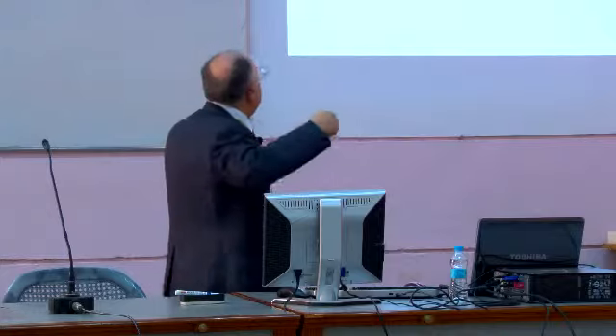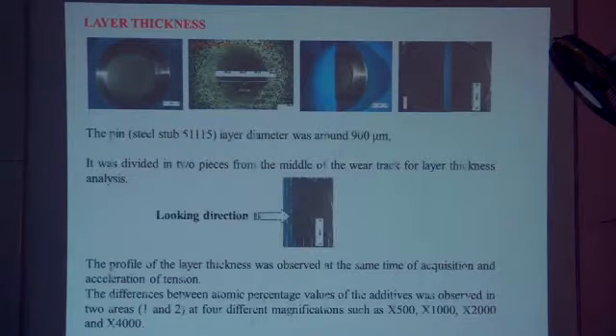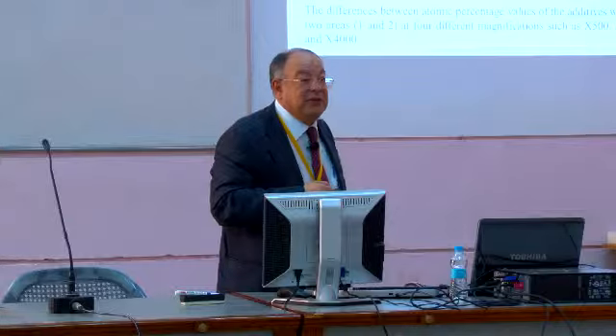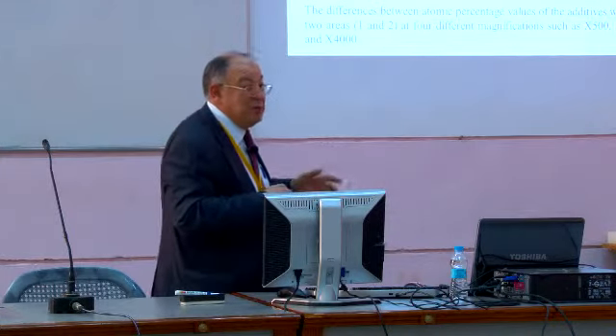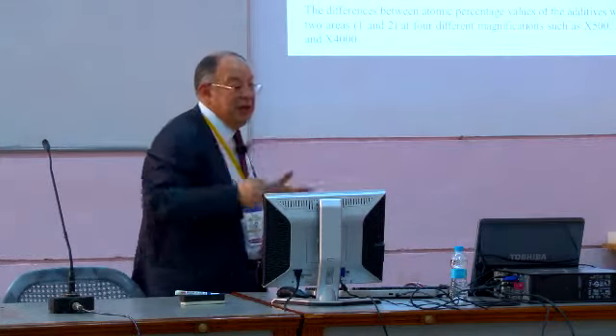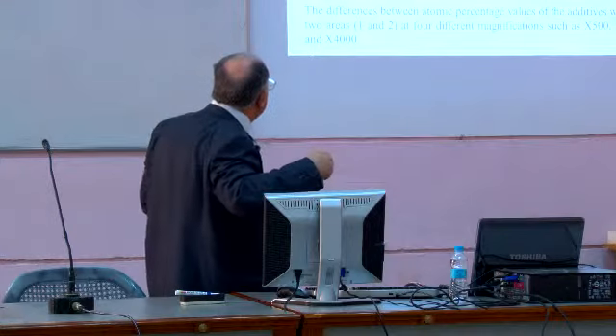Material 51115, and we tried to measure the layer thickness. So you see the pin, this is the pin surface, and we could cut it in two parts and look at that direction. At different magnifications, we could detect the thickness by AFM. It was very difficult, but maybe I was lucky, and it was very interesting.